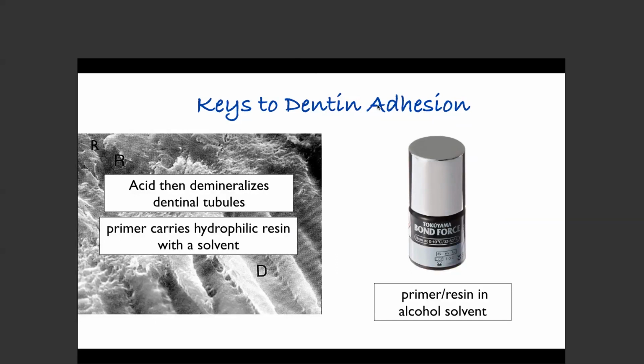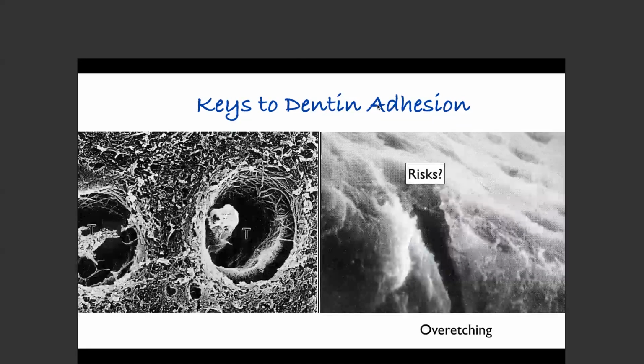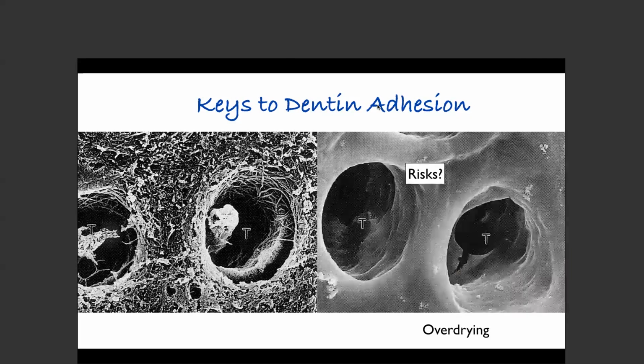So the acid is going to demineralize the dentin tubules from your phosphoric acid or your self-etch dentin adhesion system, and your primer is going to carry your hydrophilic resin with a solvent into the dentinal tubules. What are the risks? What are the things that we want to avoid? On the left is an appropriate matrix, an electron micrograph of what we want dentinal tube structure to look like. One of the risks is over etching, which you see on the right. The other risk is over drying.